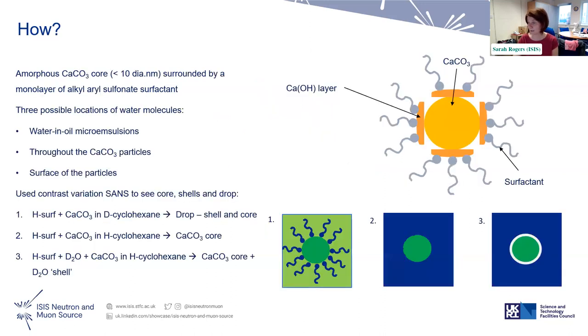So how do we do that? So they had an idea of what these particles look like. They're basically an amorphous calcium carbonate nanoparticle, which is about 10 nanometers. And they thought it was surrounded by this monolayer of surfactant, which stabilizes it. But what they didn't know is, when you have water, where does the water go and how does it actually destabilize the particles? So there were three possible locations.